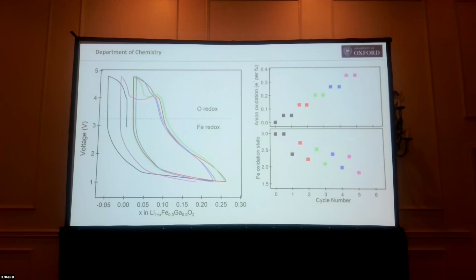As we go through the cycles again and again, what we see is we oxidize more and more oxygen, because that's irreversible. And we're suppressing the iron oxidation state further and further down. So we end up in a situation where we can't put any more lithium in the system because we're already at iron 2. You'll notice from the diagram that we have an iron oxidation state that's less than 2, but that's just a feature of us choosing this potential as the cutoff between iron oxidation and anion oxidation. I'm sure there's a bit of crossover.